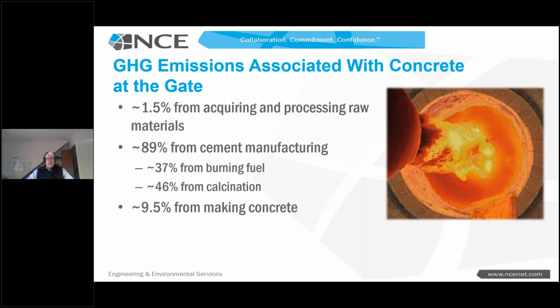We can go out, we can dig a hole, we can mine limestone, we can mine clay, shale, process it, get it ready to feed it into a kiln, and that's only about 1.5% of the total greenhouse gases associated with the production of that cement or that concrete. 89%, almost 90%, is from actually burning those raw materials in a cement kiln. 37% of that is from the fuel being used, but 46% of all of the CO2 associated with a cubic yard of concrete at the gate of a concrete plant is from taking that limestone, converting it from calcium carbonate to calcium oxide and CO2. And so a tremendous amount of CO2 is being liberated from burning limestone.